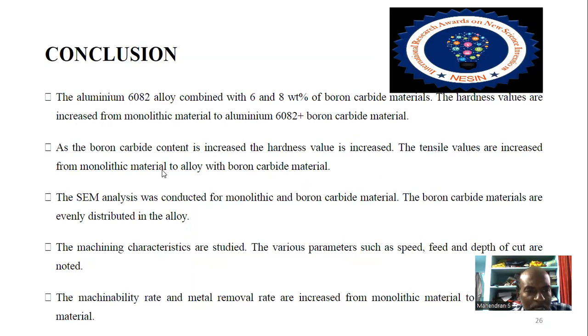Next one is the SEM analysis. The SEM analysis was conducted for monolithic and boron carbide material. The boron carbide materials are evenly distributed in that alloy. There is 8% weight ratio of the boron carbide plus aluminum composite material. The boron carbide materials are evenly distributed in that alloy.